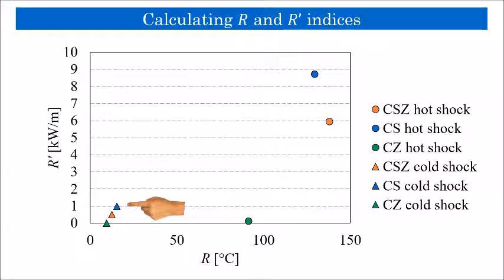In addition, hot shock resistance of CS seems to be superior for mild shock and comparatively good for hard shock scenario. In conclusion, addition of silicon carbide has enhanced resistance to hot shock and cold shock in both regimes of sudden and gradual temperature change, which affirms the validity of our original hypothesis.